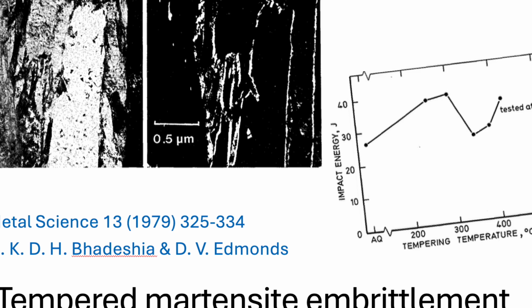Exactly. We're looking at something called tempered martensite embrittlement, TME for short. It's a really foundational problem in metallurgy, actually. Why foundational? Because it happens right in the middle of the heat treatment process, the very process that's designed to maximize toughness. It's quite counterintuitive. Fascinating. So you put this through all this effort, quenching, tempering, and the process itself introduces a potentially fatal flaw.